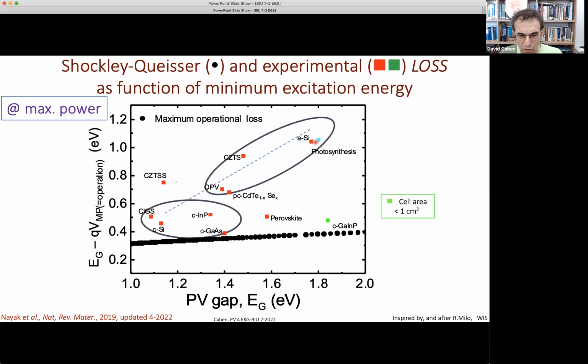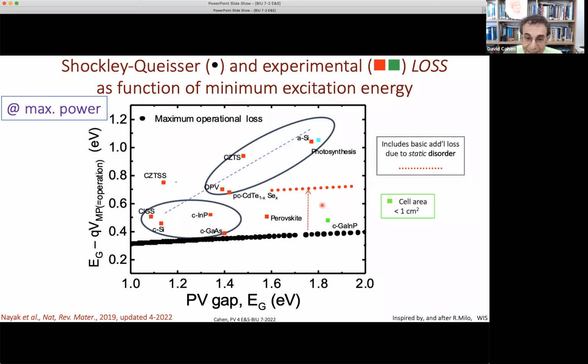Now here's amorphous silicon, here's photosynthesis. And there is something that's not entirely fair, because it was shown in the 80s that if you have a disordered system, statically disordered, like amorphous silicon will be, and photosynthesis is, then you lose about this amount of voltage to start with. Doesn't help me for practice, but for fundamental understanding, it's important to take it into account. So let's look later, we'll go back to this, at what's happening here.